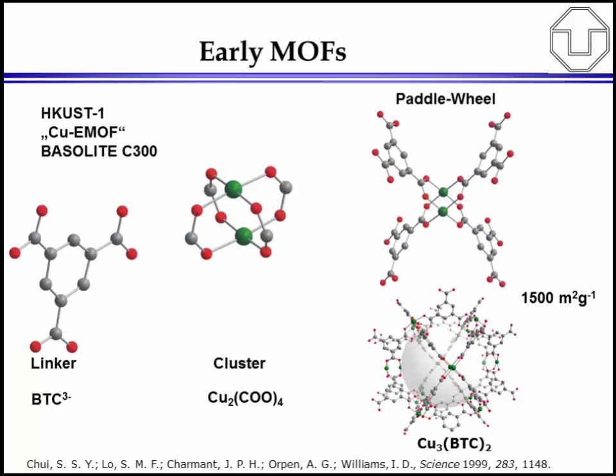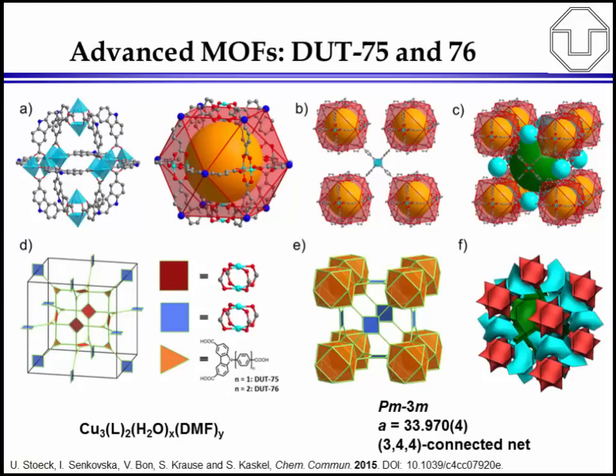But nowadays we can achieve much higher surface area, and the next slide shows one of the recent examples from my group, which is DUT-75 and DUT-76. Yeah, we name our materials after the university, Dresden University of Technology. This is the local patriotism associated with MOF researchers, and this is a material that we discovered recently, which now uses these square planar paddle wheel units, as you can see on the left upper corner A, and these square planar units are now connected with a somewhat bent carbazole type linker to form metal organic polyhedra.